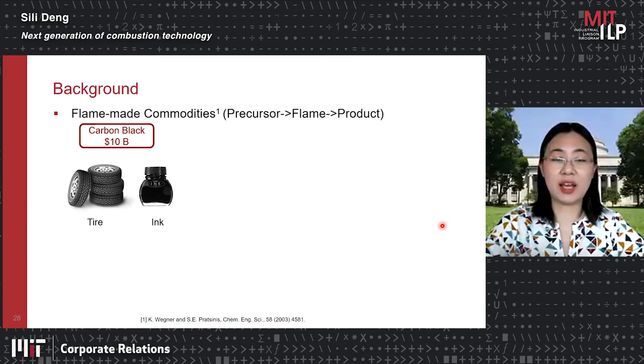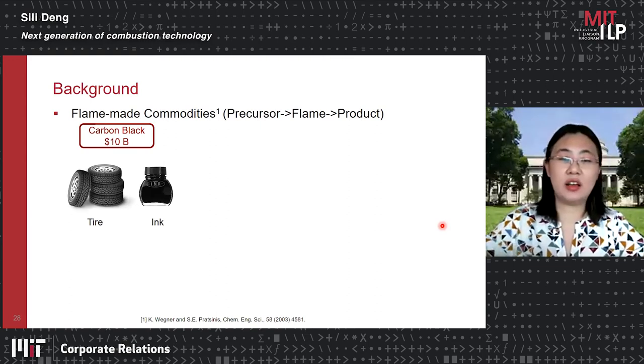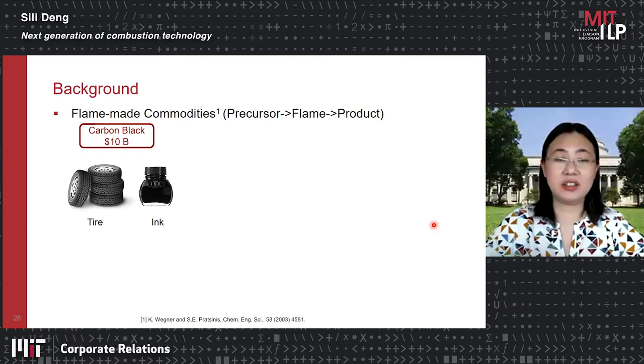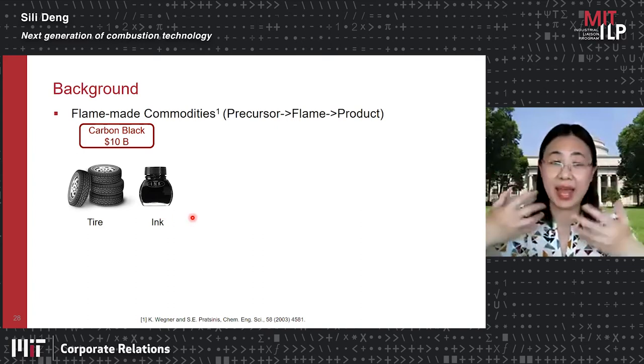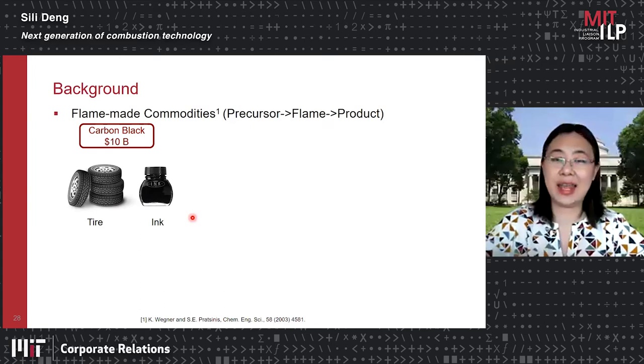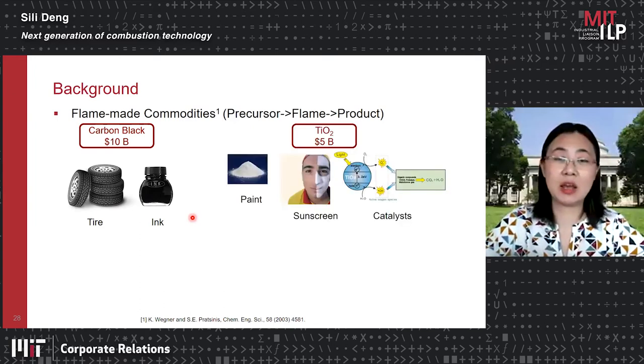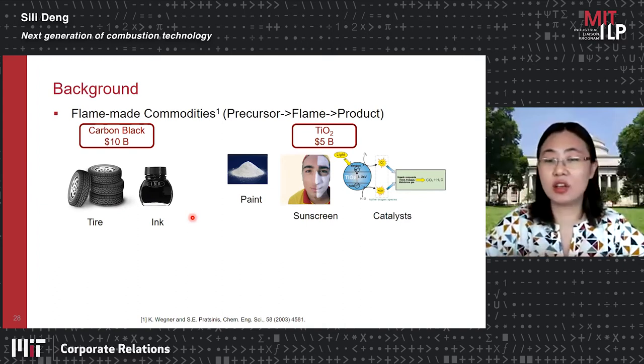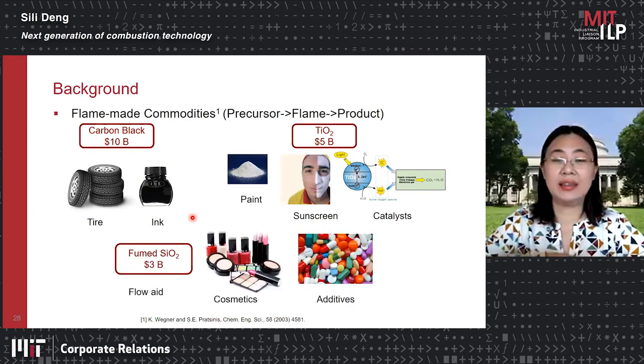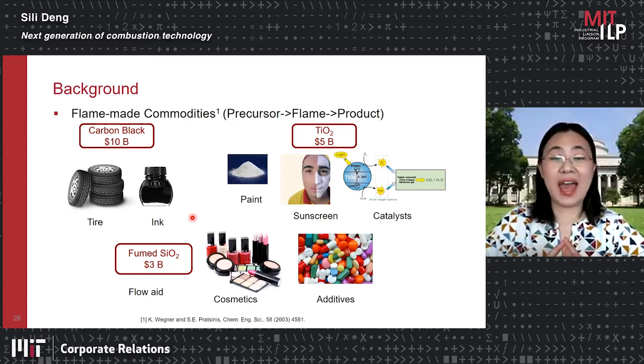First of all, on the market, there are actually three kinds of flame-made commodities. And the carbon black is basically just the soot particles, but in a controlled way. So you can gather them afterwards and use them in tire and ink. And second group is the titanium oxide, which is widely used as white pigment and in some sunscreen products. And for some nano-sized or sub-micro-sized, you can use them for catalysts for many things. And the fumed silica or silicon oxide is a very useful flow additive to enhance the flow characteristics.